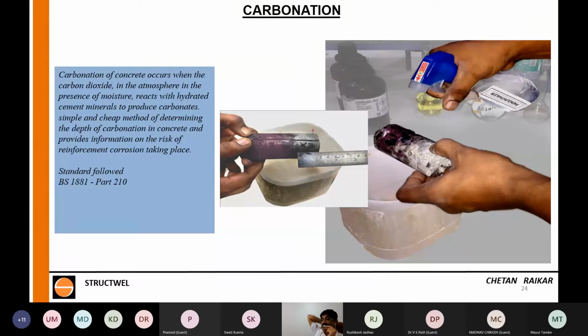This carbonation falsely increases the Schmidt hammer, rebound hammer value. Sometimes if you take Schmidt hammer readings on an old building and do the coring, the core results are much lower compared to the hammer reading, because of carbonation, there is a false increase in the rebound number. But this is how the concrete turns.